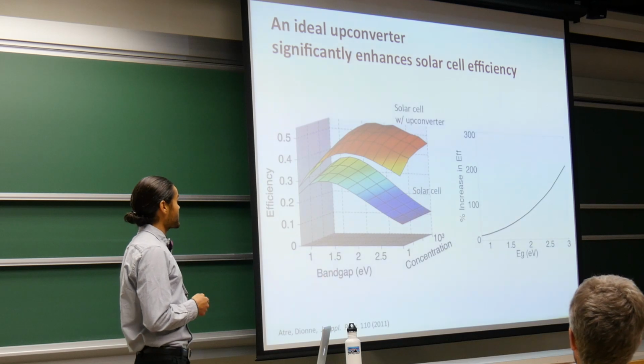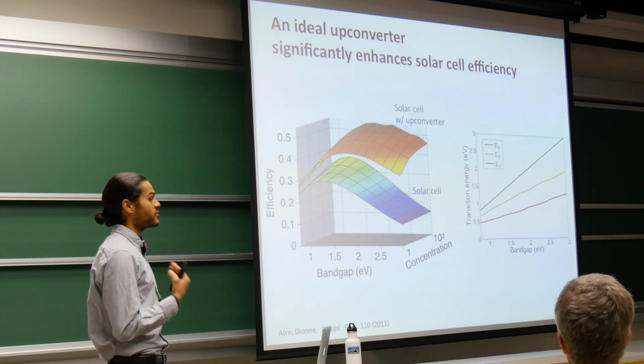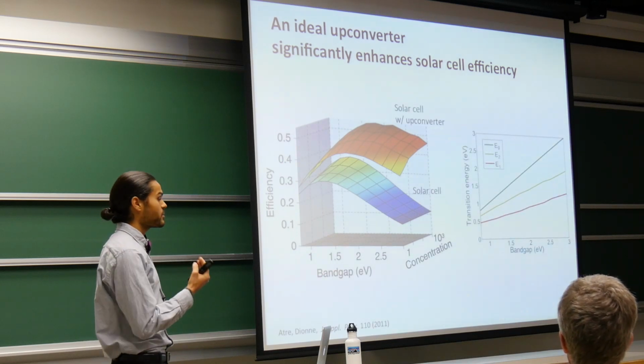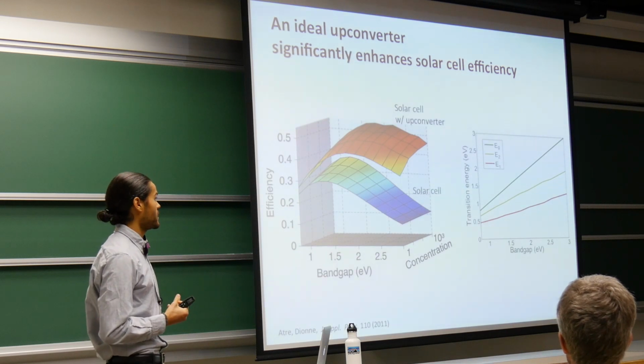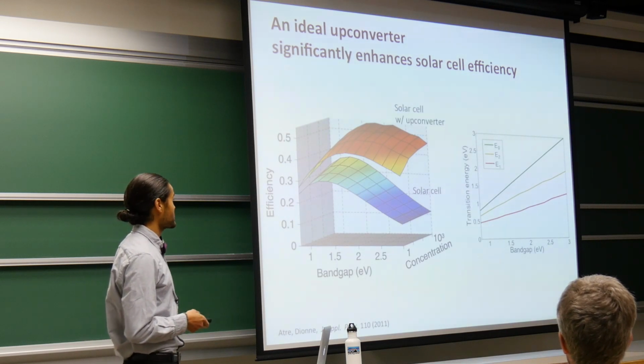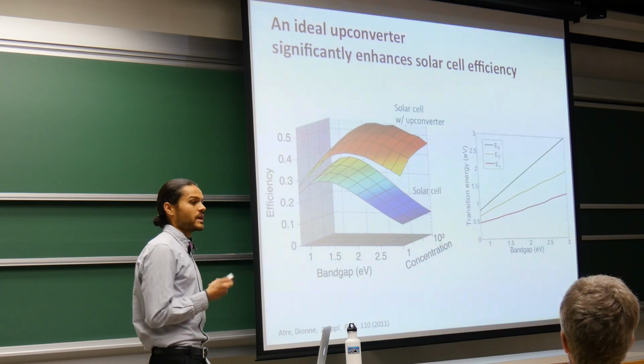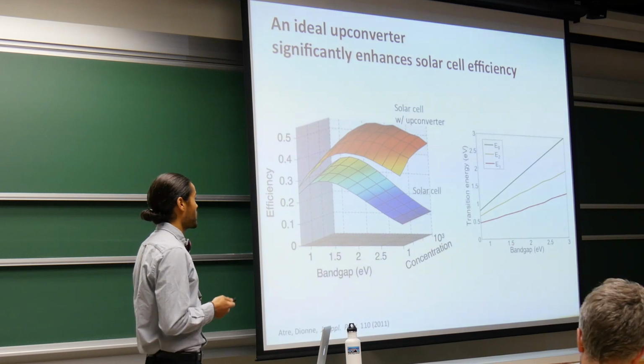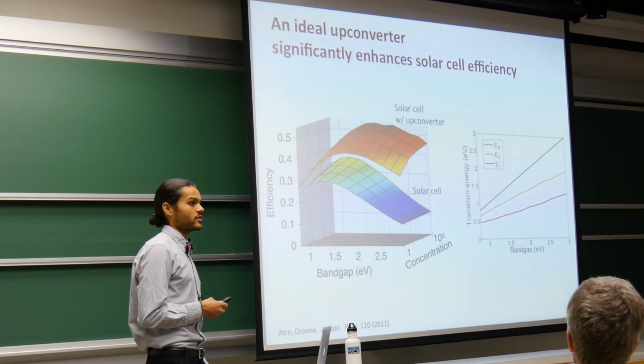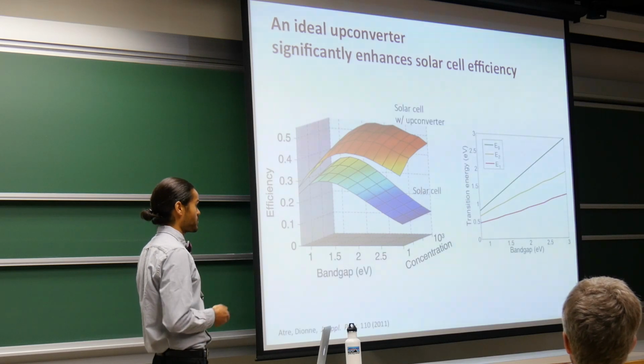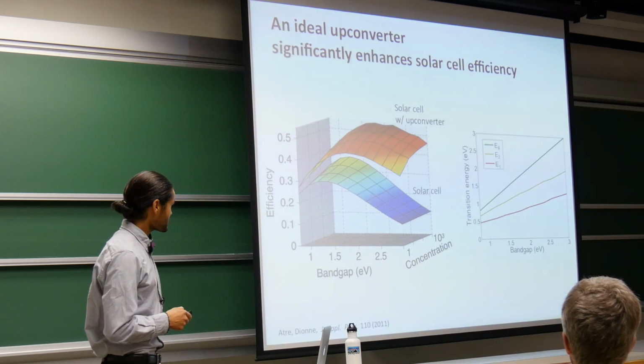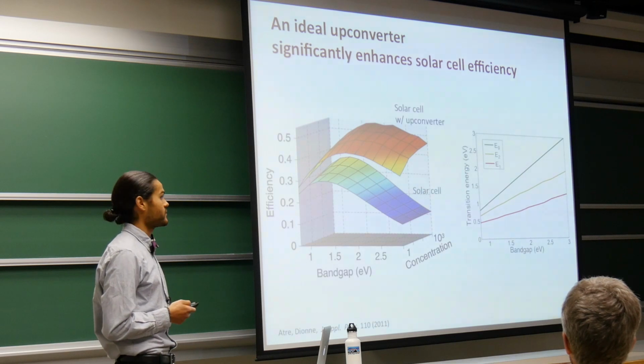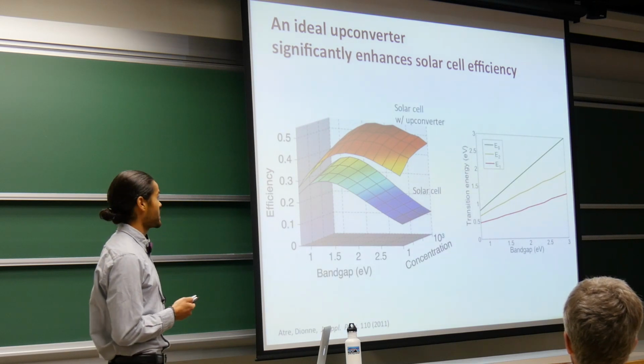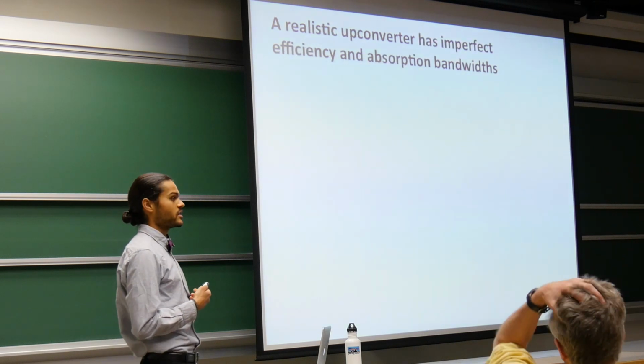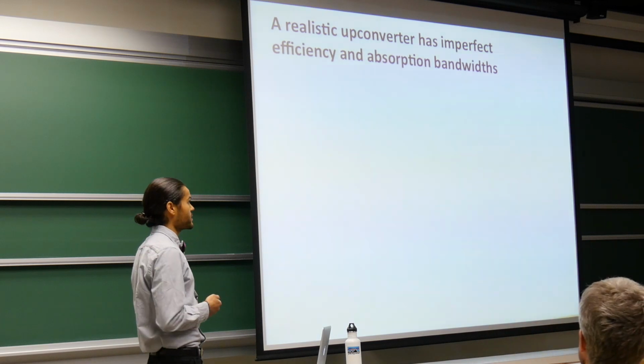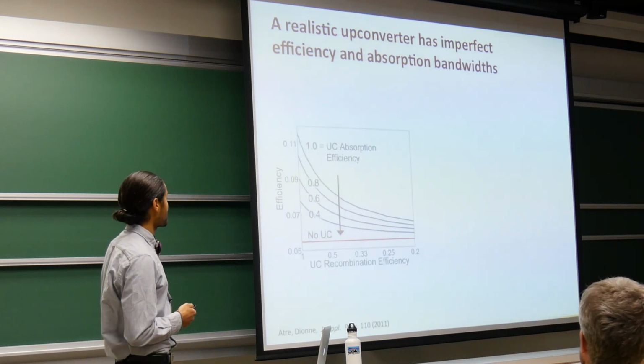Another interesting thing that we can get from this model is some information about the properties of the ideal upconverter that we might like to design. In this case, this plot shows you, for a given band gap of solar cell that you want to work with, what energies of the upconverter would be the best in terms of improving the efficiency by the most. All of these calculations that I've just showed you are for ideal conditions, however. So it's important to consider how a realistic upconverter and a realistic solar cell change this story.